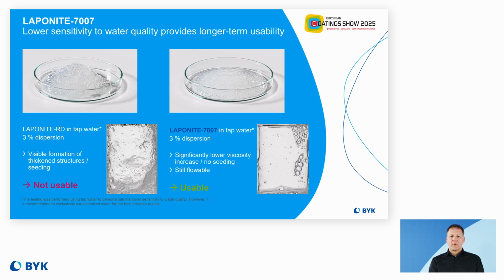To show the performance advantage, we incorporate 3% of the additive in tap water. I know you all know that you should usually not use tap water, but this is just to show you the advantages of the product. When you wait a bit, you see that LAPONITE RD in tap water very quickly creates a gel, while with LAPONITE-7007 we notice a nice liquid and we don't see any seeds. This is a huge advantage for your paint application.